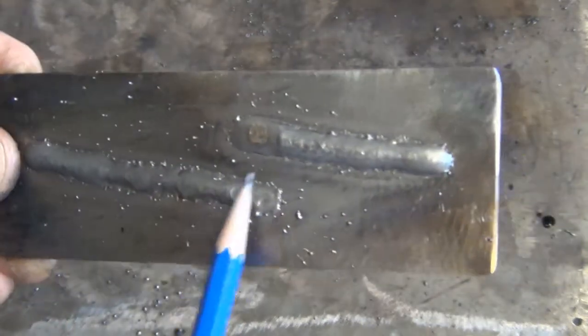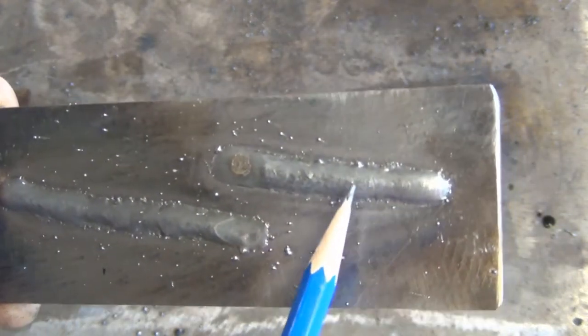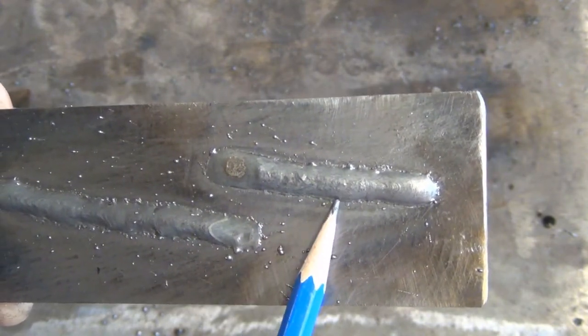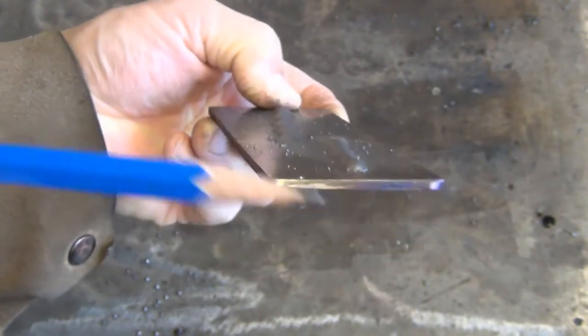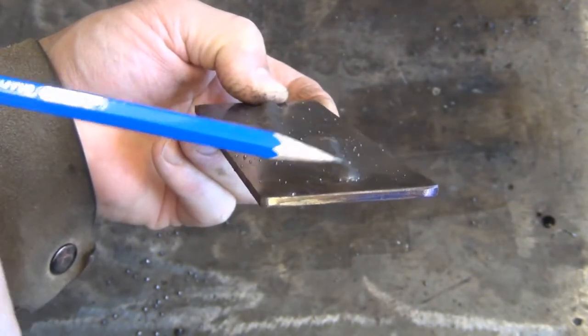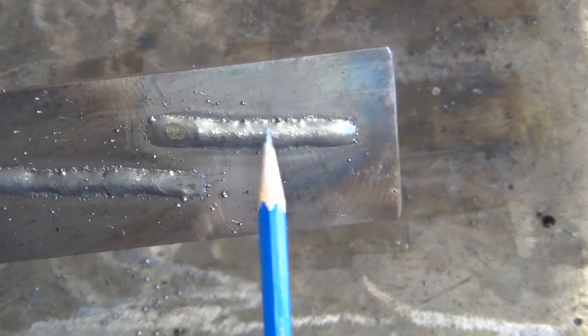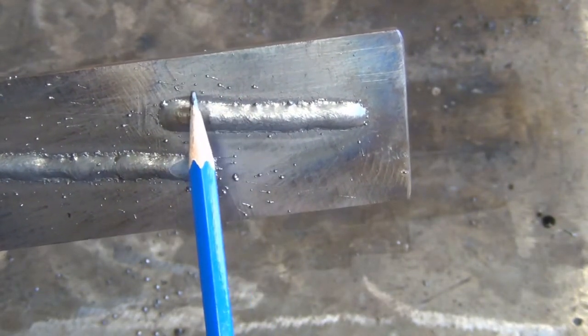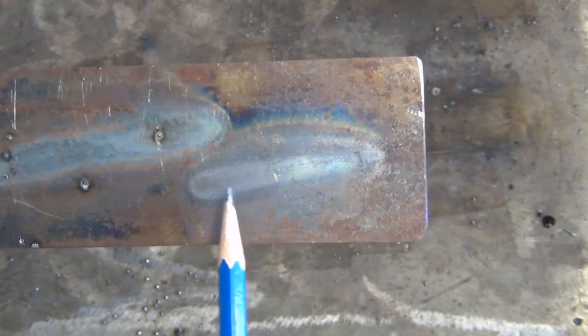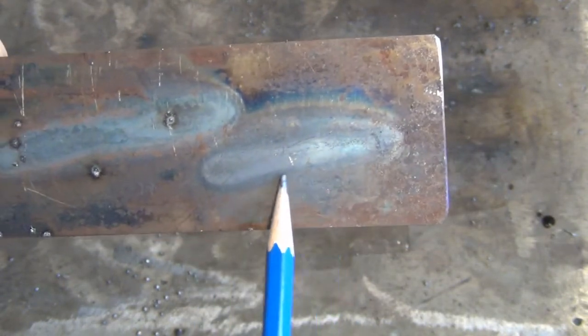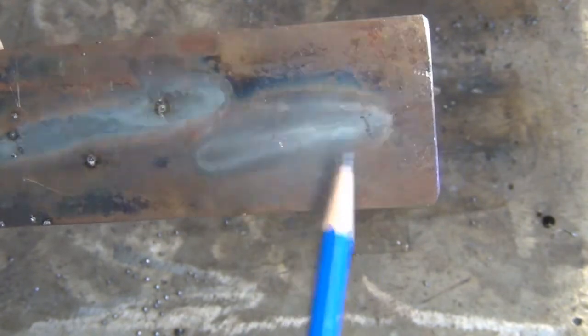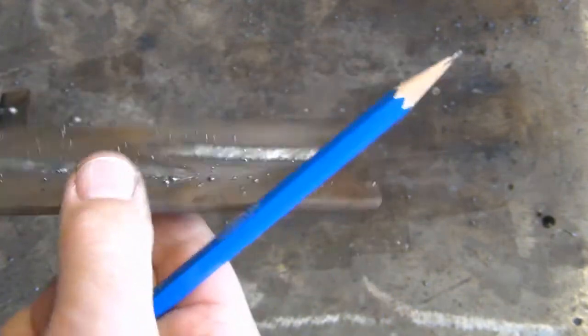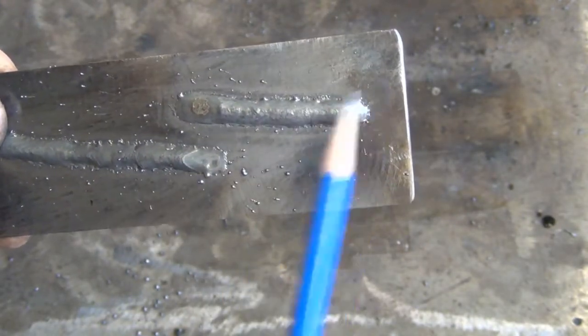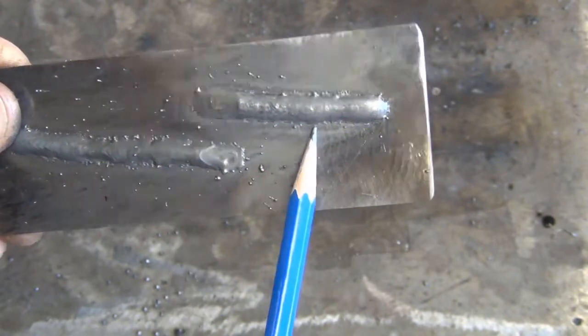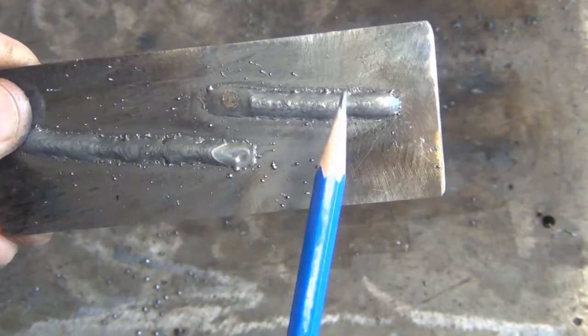Now here we're looking at a weld like we want to see. Okay? The width of the weld is about twice the height. Okay? So that's what we want. There's a little bit of spatter, not much, just a little. And when I turn the piece over, I can see that the heat penetrated right through the host material. So I've got good penetration, I've got good weld form. I would continue on my weldment using where the welder is right now.